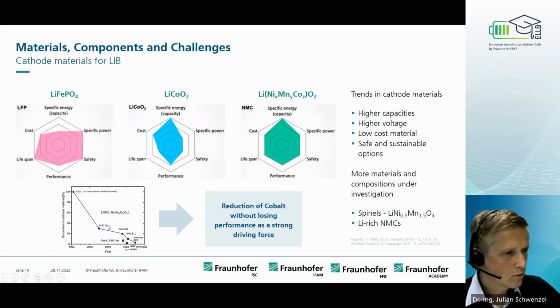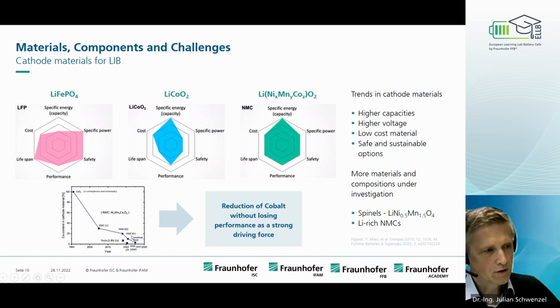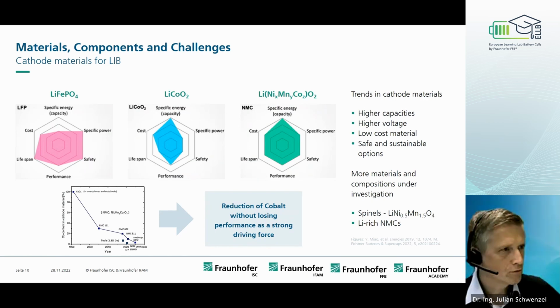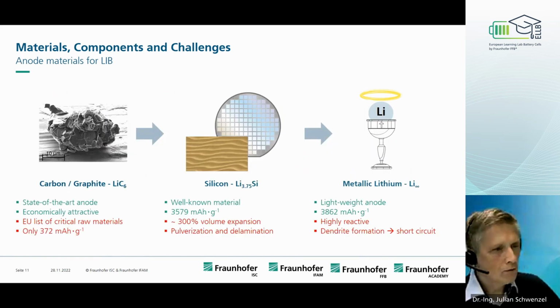It means like 111 or 622. So this is a composition. And if you look here, 811 means we have a high nickel content and a low cobalt content. So here it could really reduce the amount of cobalt. But then further ideas, maybe cobalt-free systems, this nickel manganese oxide system, are available in development. So the reduction of cobalt without losing performance is a strong driving force in the development of future lithium-ion battery technology. So if you now look at the other side, the anode side is also very important here.